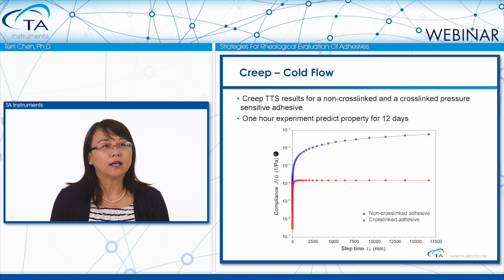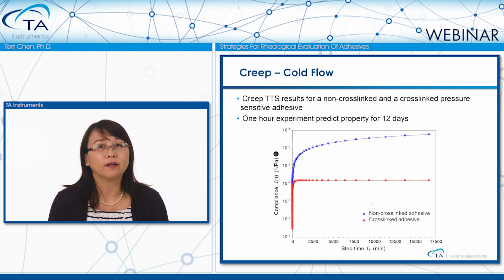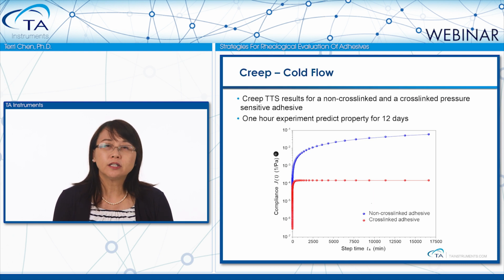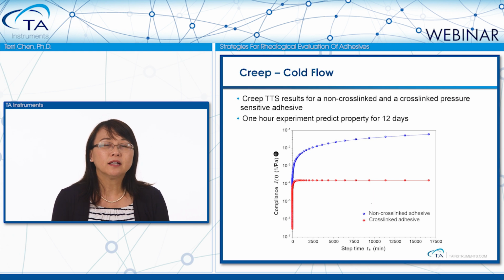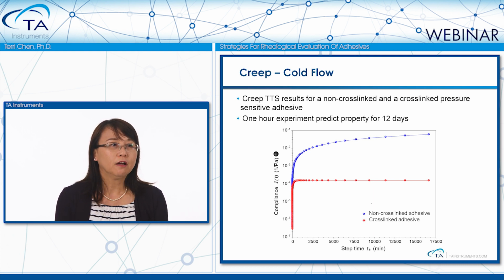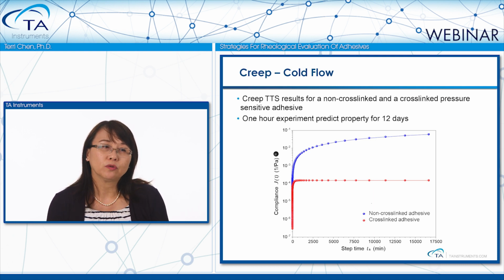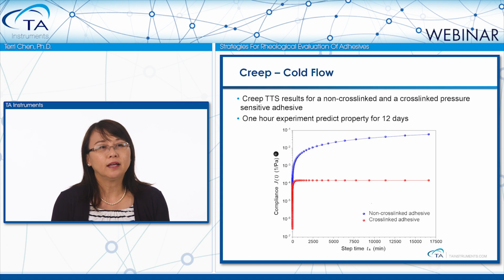Here is an overlay of two creep TTS results of a non-cross-linked and a cross-linked PSA sample. Each TTS test takes only about 1 hour, but the analysis results can be used to predict the property over 10 to 12 days. From these measurement results, we can clearly see that the non-crosslinked adhesive has significant creep over time. It displays poor shear resistance to cold flow.